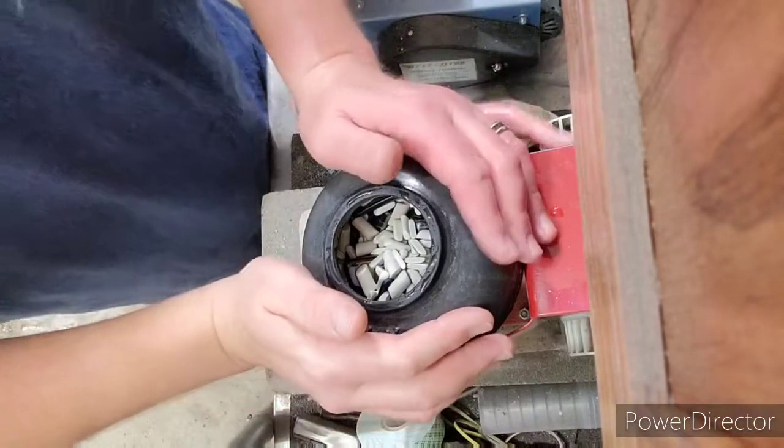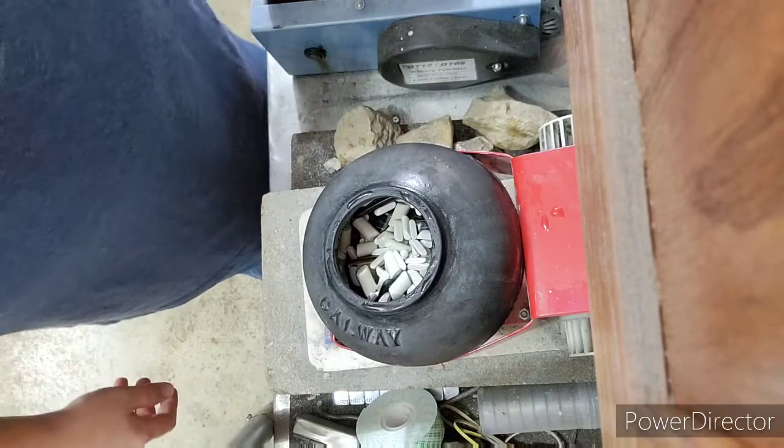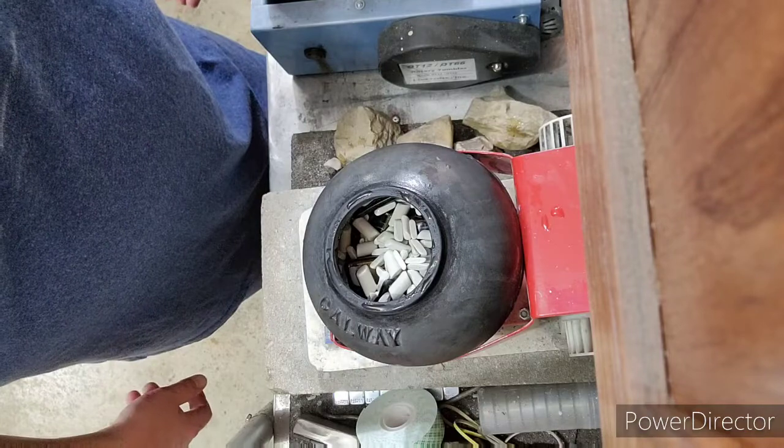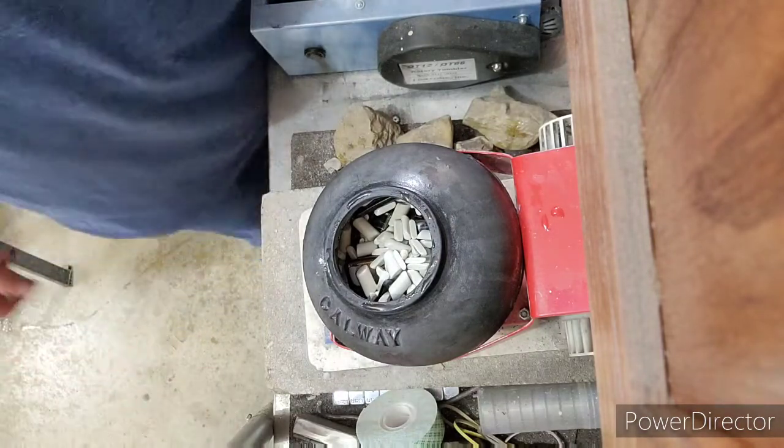All right, the rocks and the barrel are all cleaned up really well and everything in the barrel is wet, no standing water. We're going to get going to the polish stage. It'll be a half a teaspoon of the aluminum oxide polish and a tablespoon of borax, and we'll go for another 3 days on it.